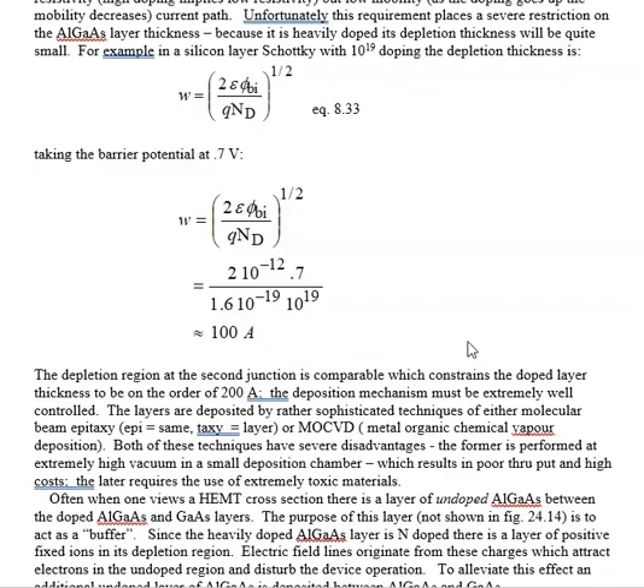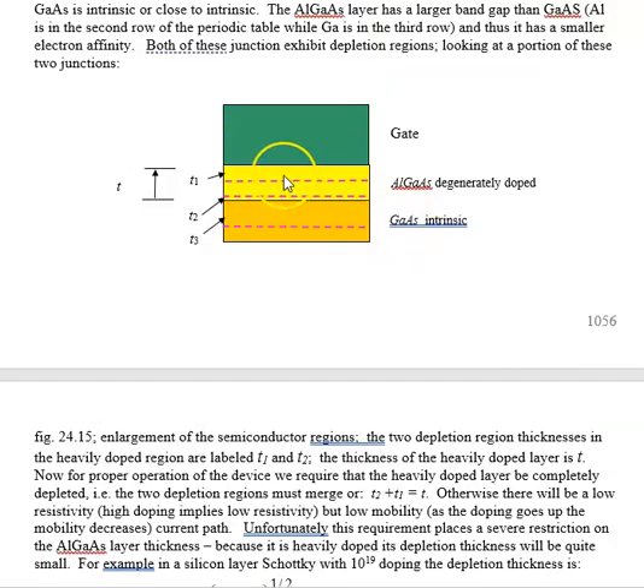And now there's one more consideration. If you take a course in wideband semiconductors, they give all kinds of graphs and pictures and maybe even some calculations. But the idea here is that we have a depletion region here. And if we have a depletion region in N-type gallium aluminum arsenide, we're going to have lots of positive fixed ions. So we have lots of positive charges right up here, and those charges produce electric field lines, which will end in the channel. So that's not good, because they're going to be centers for scattering and lowering the mobility. So what we do is, between the yellow and the orange, we put what we call a spacer layer of undoped or intrinsic gallium arsenide to kind of suck up some of those positive charges.